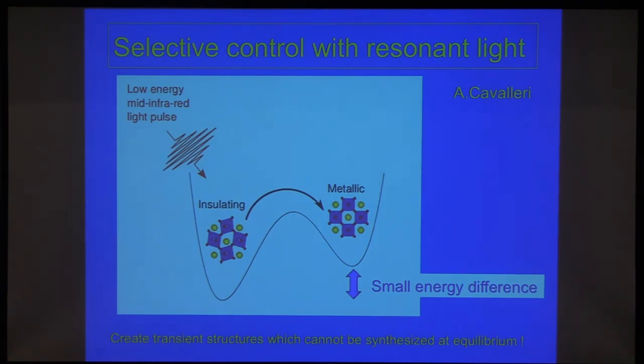The fact that the energy landscape of these materials is complex and there are many phases also suggests that there may be neighboring phases which are not really stable at equilibrium, but which may be separated from the true equilibrium phase by a small energy difference. And the idea is, by shooting at this material a carefully engineered laser pulse, for example, whose energy is resonating with a specific structural mode of the material, can we actually change the structure into a new structure which would not be the stable equilibrium structure and which would have a different electronic functionality? And so this has been demonstrated in the lab. The pioneer of this field is actually Andrea Cavalleri, now in Hamburg.